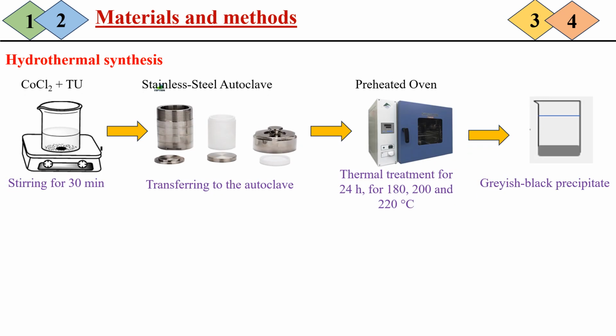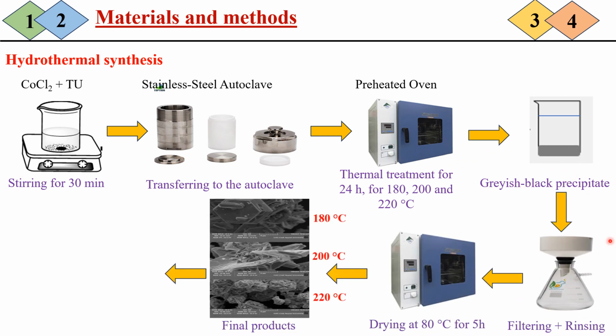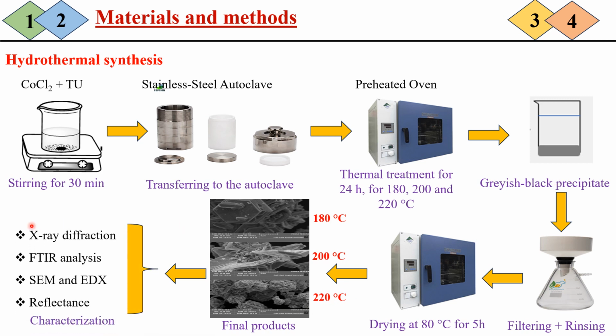Now, let's talk about the second section and let's begin with the hydrothermal synthesis of our materials. Firstly, we mixed cobalt chloride and urea in distilled water for 30 minutes. The mixture was transferred to a stainless steel autoclave, then to an oven to undergo a heat treatment at different temperatures for 1 day. After the heat treatment, we recovered a greyish black precipitate which was filtered and rinsed using distilled water and ethanol. After that, we dried our product before being characterized using X-ray diffraction, FTIR analysis, SEM and EDX, and reflectance.